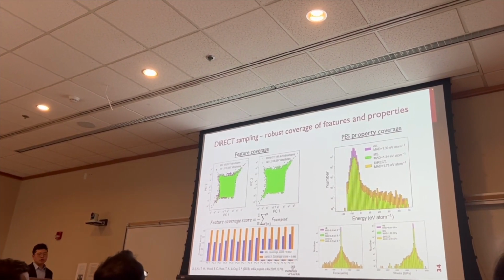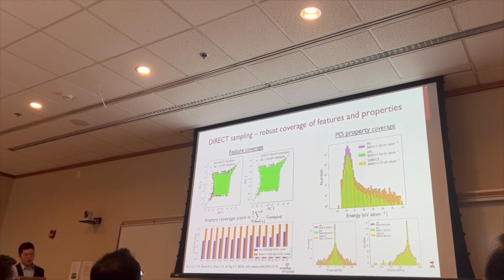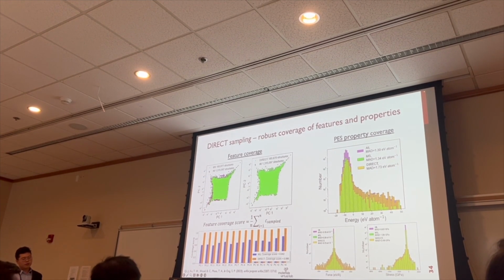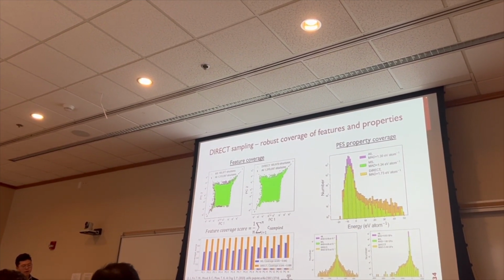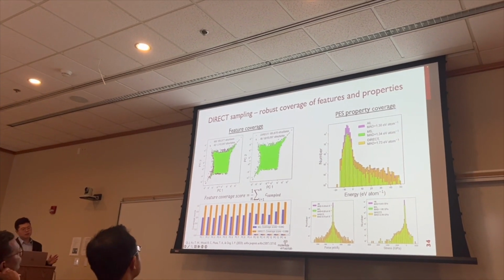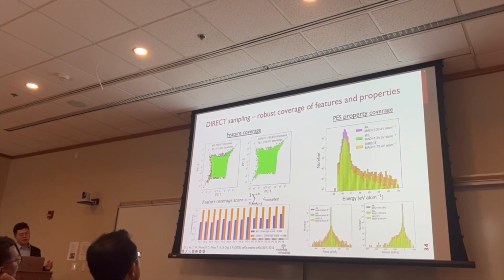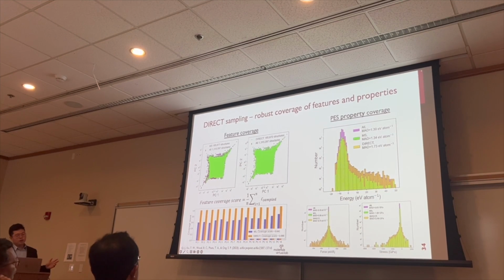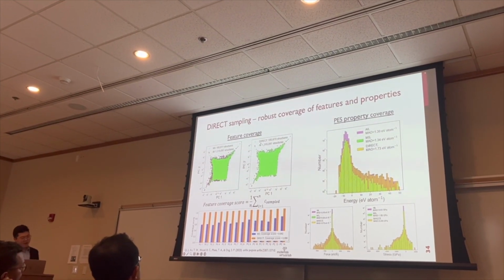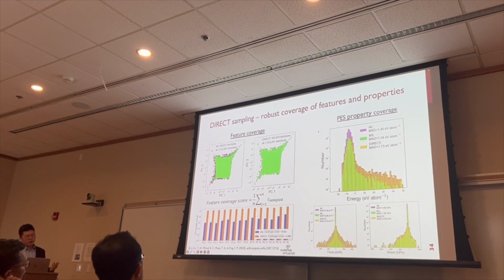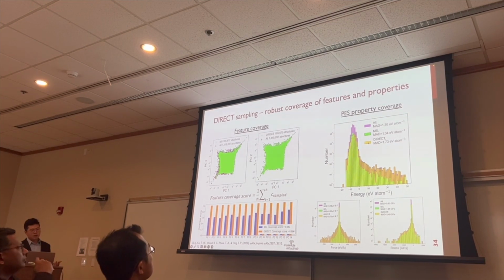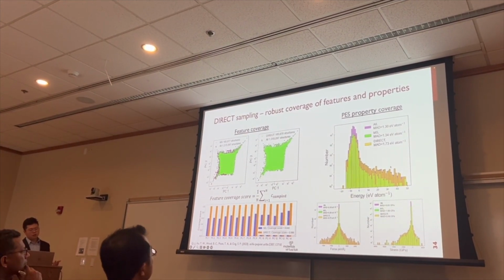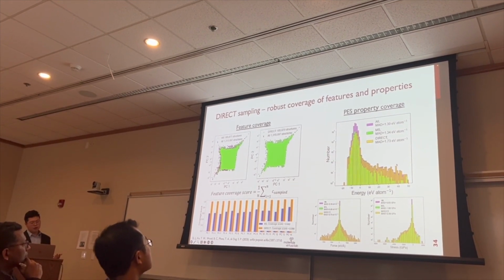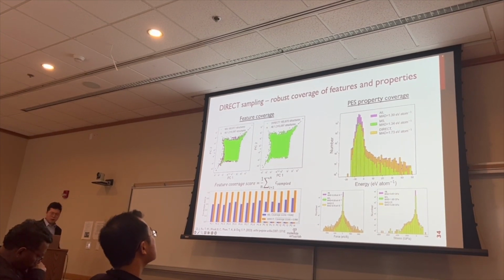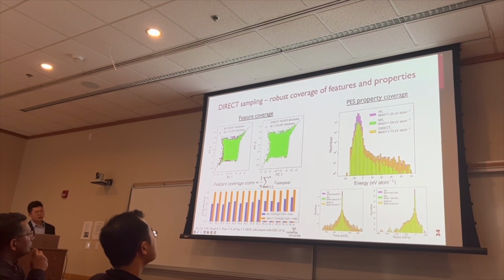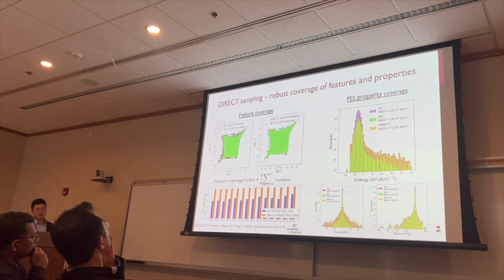And by looking at the coverage of this direct sampling and comparing with the manual sampling, we can see firstly in the feature space, the previously uncovered boundaries of feature space is covered. And I want to mention that this direct sample dataset has almost exactly the same size, which is around 15% of the total dataset, the same size as the manual sampling dataset. And also looking at the potential energy surface property coverage, we can see that the orange bars almost overlap with all those purple bars representing the total dataset for those relatively uncommon potential energy surface properties. So this slide tells us that direct sampling indeed gives a better coverage for those more diverse structures from the configuration space.